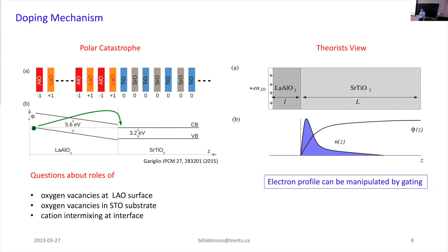And there's certainly a role for oxygen vacancies in the STO substrate, although people work very hard to control that. They tend to accumulate right at the interface and are an additional source of electrons. And then there's been a lot of discussion, I haven't seen any resolution to this, whether the fact that cations intermix at the interface plays any role in the formation of the electron gas. But that one's a little harder to understand, because if it happens, that means it's not happening until you get a threshold thickness.